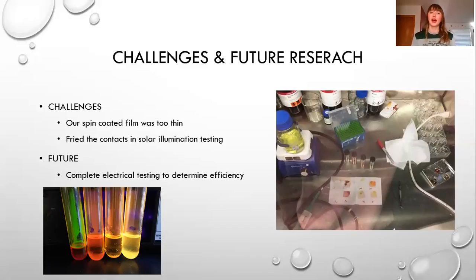And because of that, when we did solar illumination testing, basically we hooked the wires up and shine a really bright light to mimic the sun on it, we actually ended up frying our contacts. And so in this picture on the right, we've deposited a much thicker layer of quantum dots onto the solar cells. And so in the future, that should eliminate that issue.